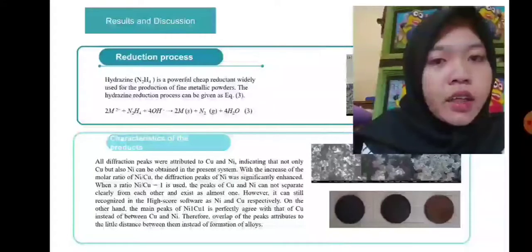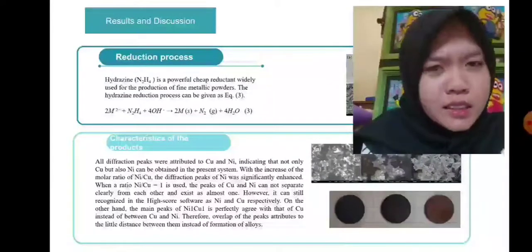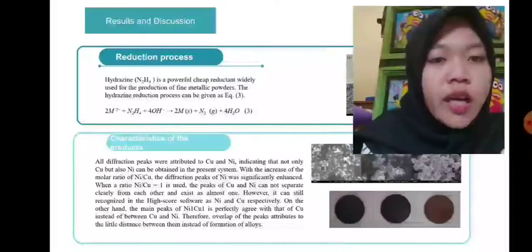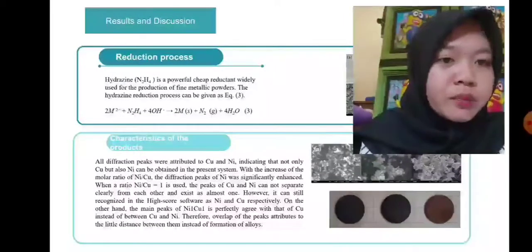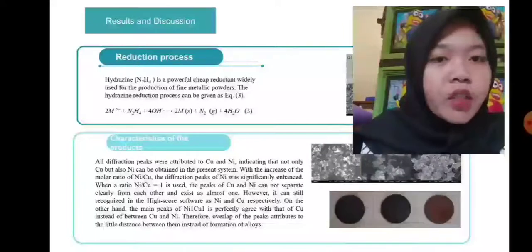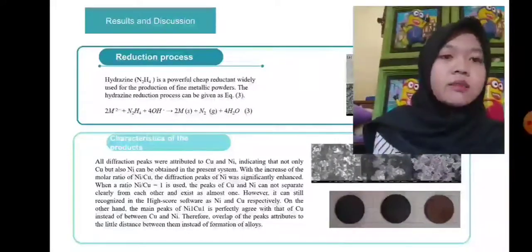However, they can still be recognized in the HighScore software as nickel and copper, respectively. On the other hand, the main peaks of nickel 1 copper 1 perfectly agree with that of copper instead of lying between copper and nickel. Therefore, the overlap of the peaks is attributed to the small distance between them instead of the formation of alloy. You can see on my PPT the pictures of the reduction process and characteristics of the product.